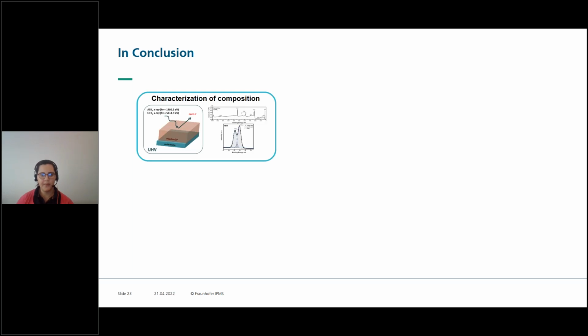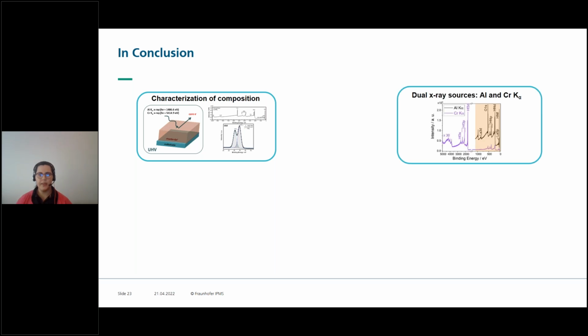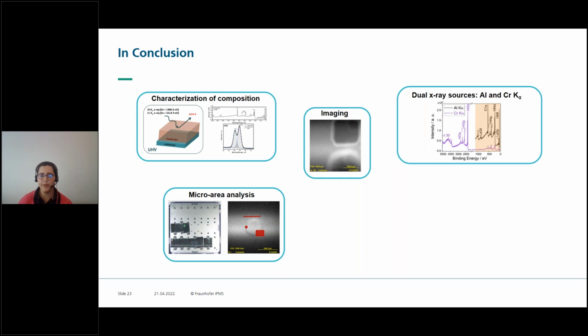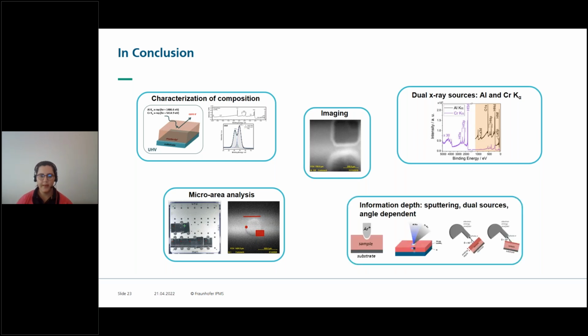Therefore, in conclusion, what we can do with our XPS technique, we can characterize composition. We can use our dual X-ray sources. We can do imaging. We can do micro area analysis. And we can look at information depth using sputtering, using our dual monochromatic sources, and using angle-dependent measurements.